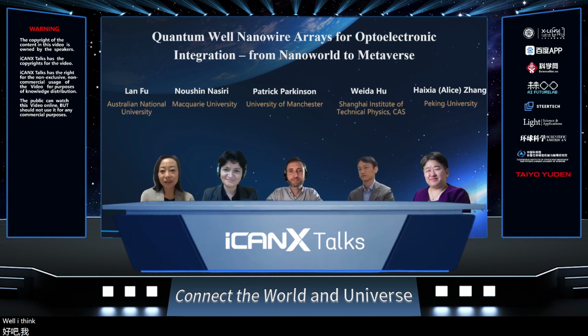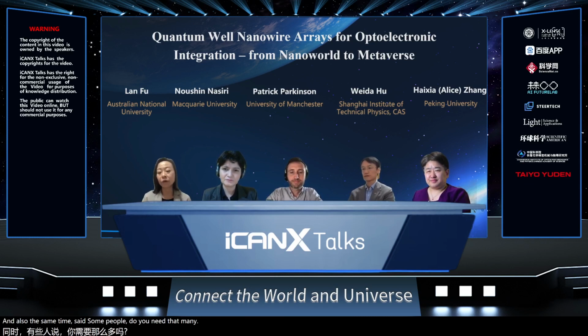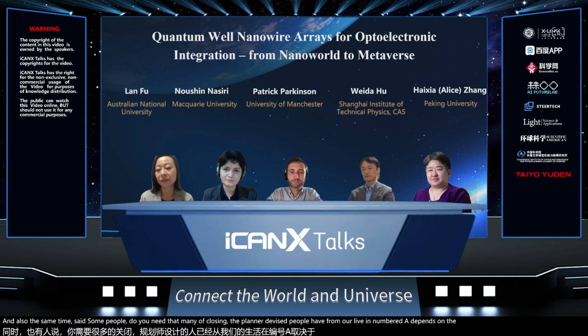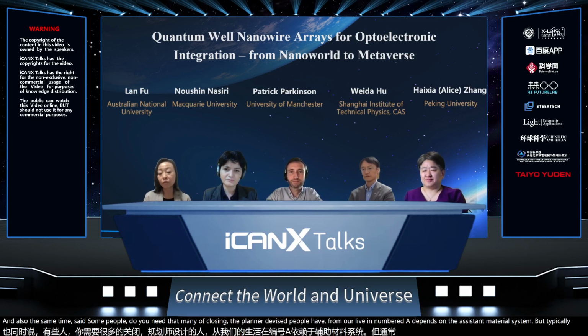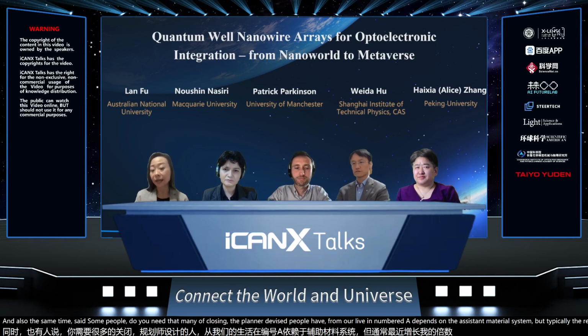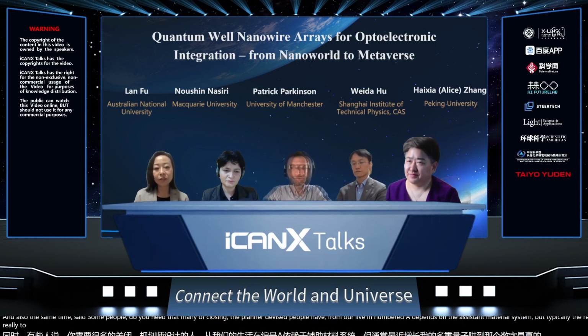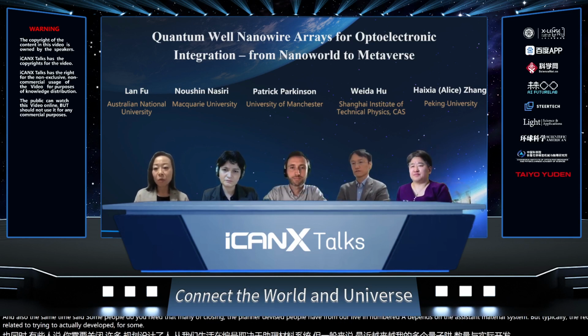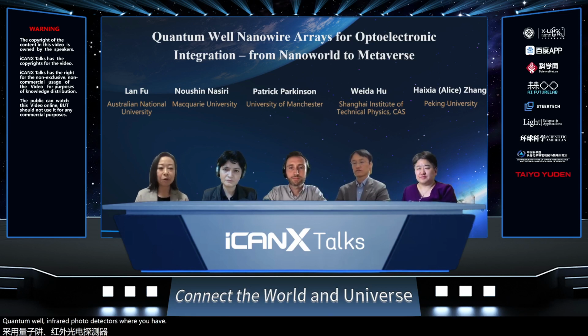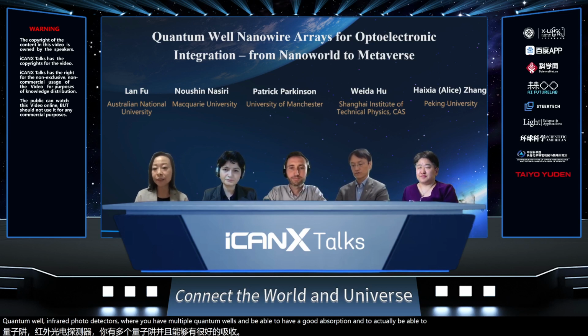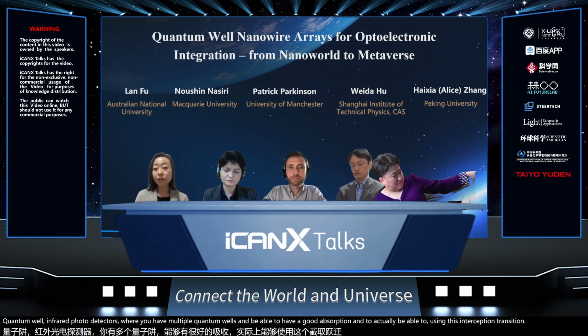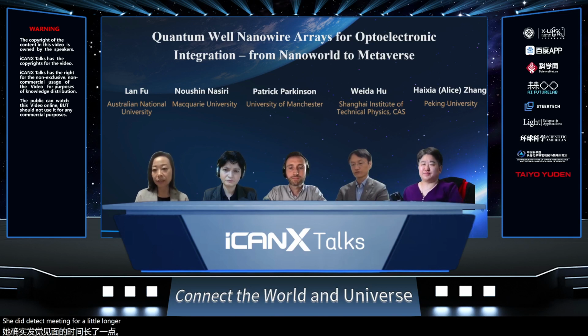Well, I think this is really coming from what we've learned from the planar device, and at the same time, do you need that many? Of course, in a planar device, people have grown an unlimited number. It depends on the material system. But typically, the reason we're growing multiple quantum wells up to that number is really to develop quantum well infrared photodetectors, where you have multiple quantum wells to get good absorption and use the inter-subband transition to detect mid-infrared to long-infrared light.